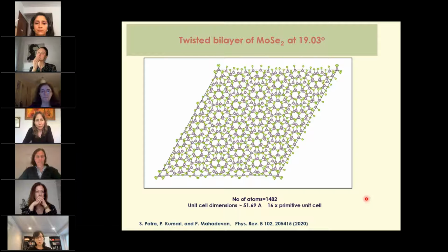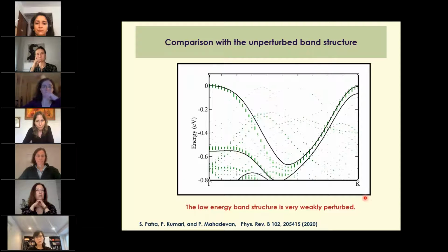And carrying out this analysis at a reasonably large angle, where there isn't the unusual correlated physics that one has seen in the context of WSe2, what I'm showing you over here is the result from our analysis where we've projected all the perturbed wave functions onto the unperturbed ones. That's shown in the green lines over here, with the width of each point indicating the weight. And the other case, we compare it with the unperturbed limit. What we find is that we recover the low energy band structure in this case, indicating that the system is very weakly perturbed, as one hypothesized, because they are indeed van der Waals materials.